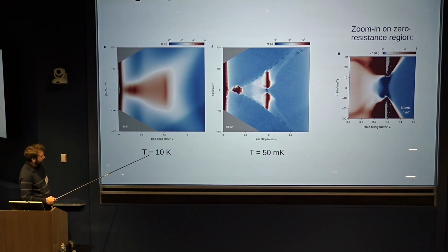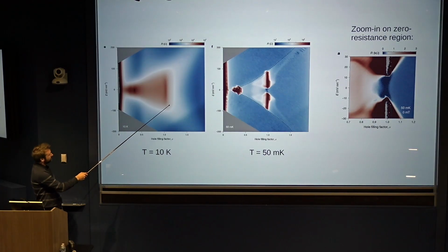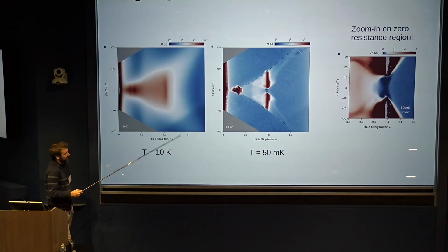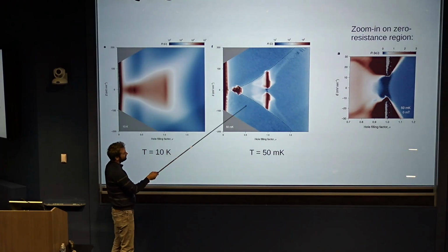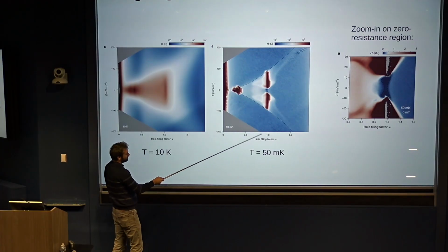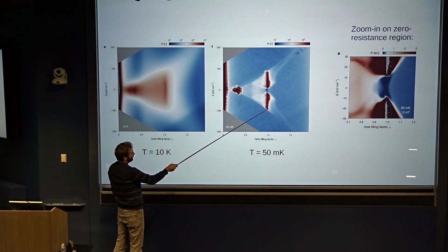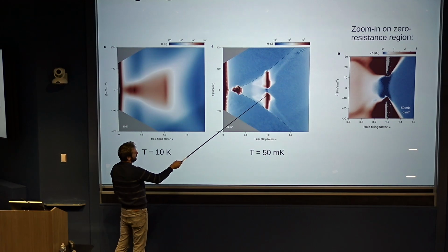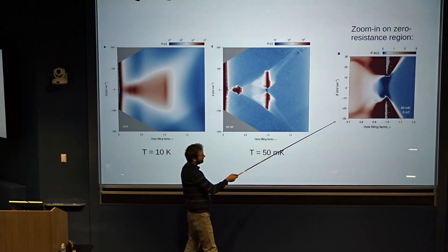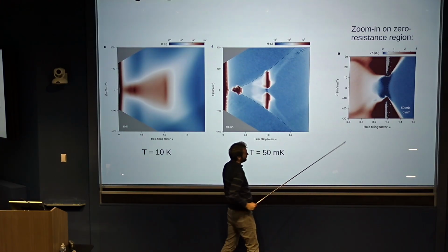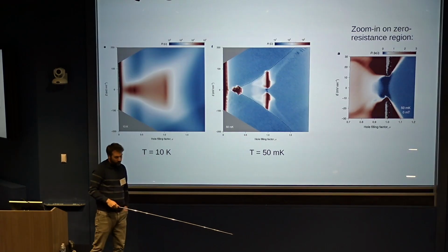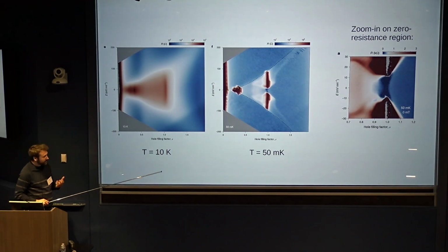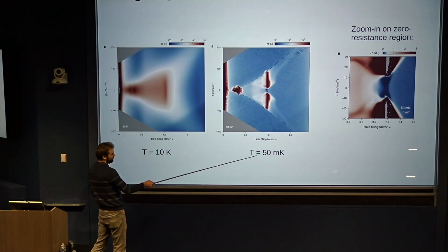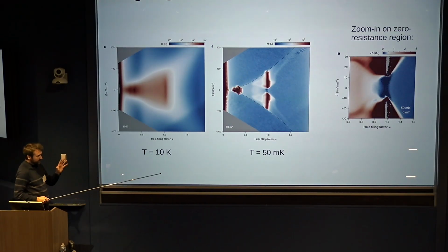What you see at a temperature of 10 Kelvin is a high resistance region emerging, starting at hole filling 1. As you cool to 50 millikelvin, you see that at this hole filling of 1 there are two high resistance regions, so two insulating regions, and then a low resistance region around zero displacement field. As you zoom in on that region, you see it's really a zero resistance region, and there's really superconductivity there. So, okay, this is not a high Tc. The Tc is higher than 50 millikelvin, but it's not very high.